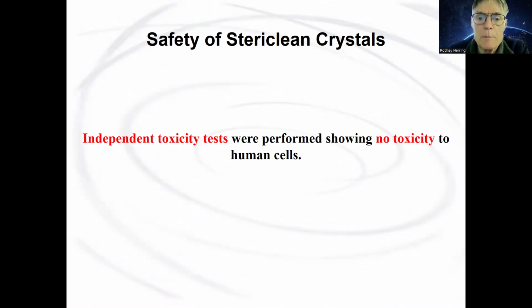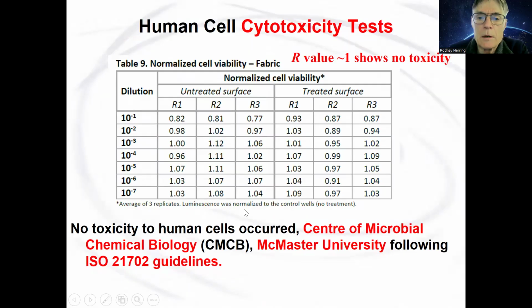We've had also independent toxicity tests specifically for our crystals, and we find there's no toxicity. So if we look here, any kind of R value of around 1 shows that there's no toxicity. This is our crystals, and there's dilutions here. So this was also conducted at the Center of Microbial Chemical Biology using these guidelines.